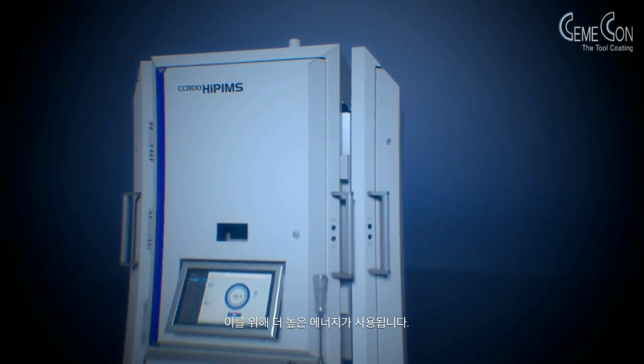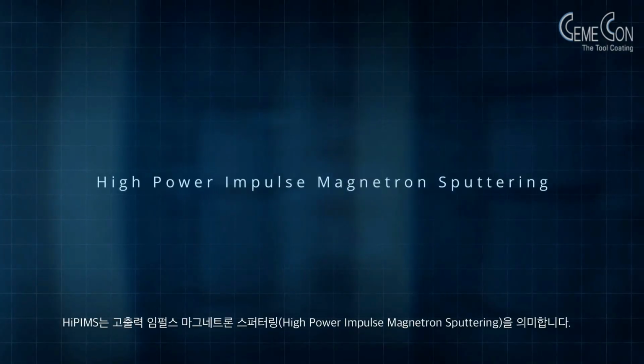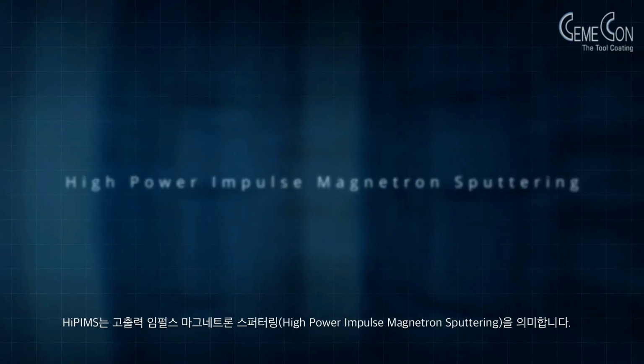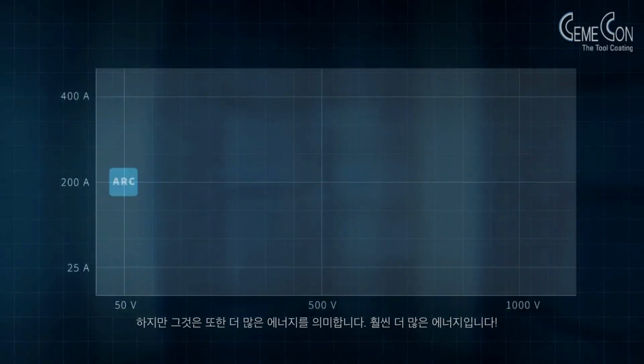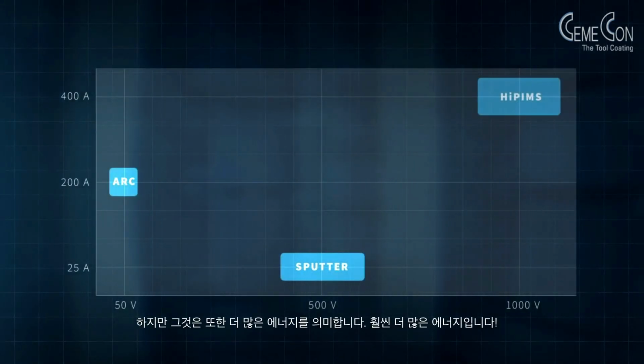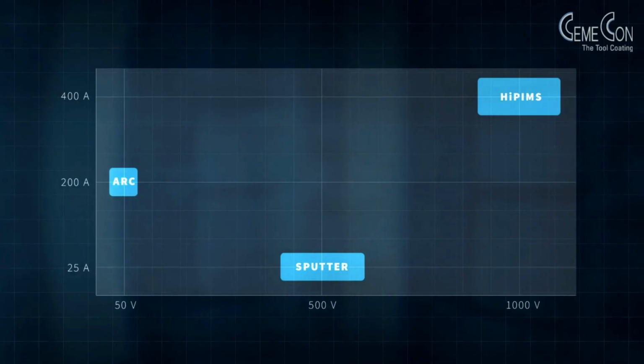The logical consequence is to generate a denser plasma than in conventional sputtering in order to achieve ionization of the donor material. This is done by using more energy. HiPIMS means high-power impulse magnetron sputtering. But it also means more energy. Much more energy.